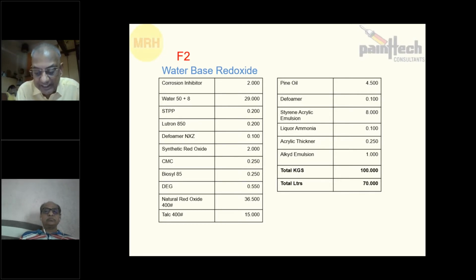For all these additives, I have one single solution. I developed an Alkyd emulsion. I struggled for 10 years to develop this product. When I was using styrene acrylic and pure acrylic normal emulsion, they used to gel after 2-3 months because of phthalic penta - I don't know exactly why - but shelf life was less. Otherwise the product was okay. Now I have overcome that problem.